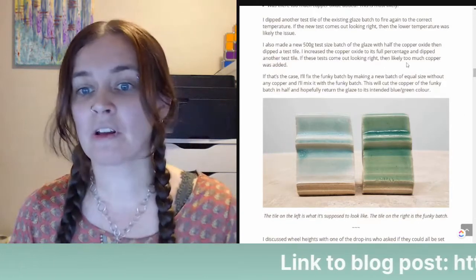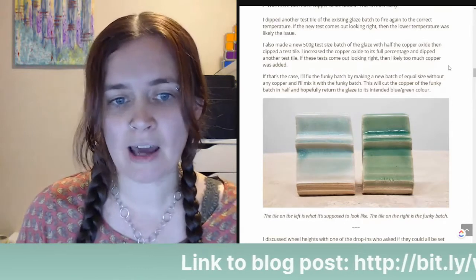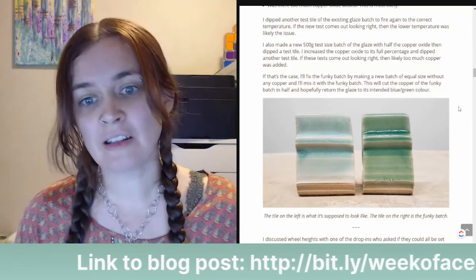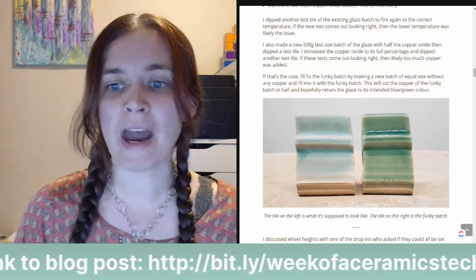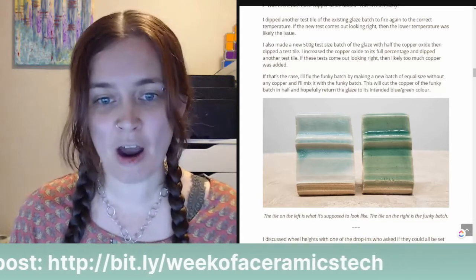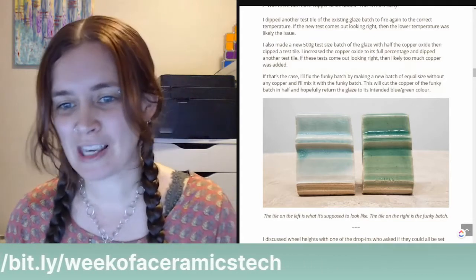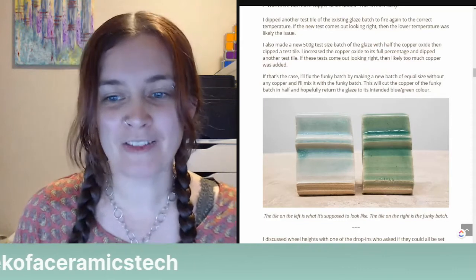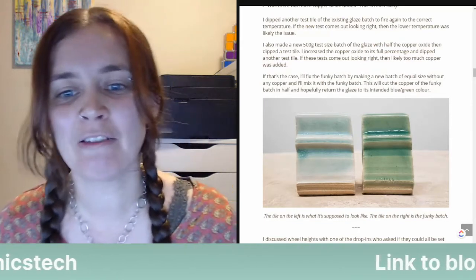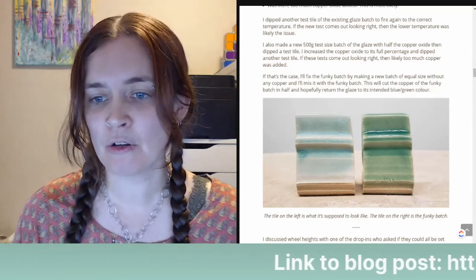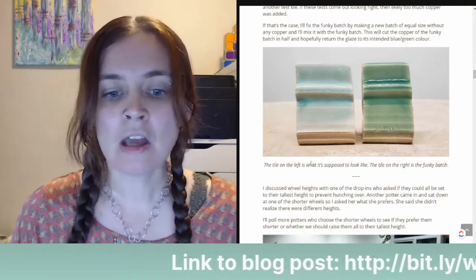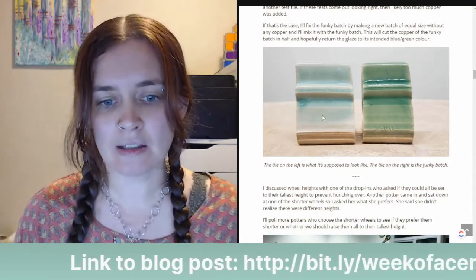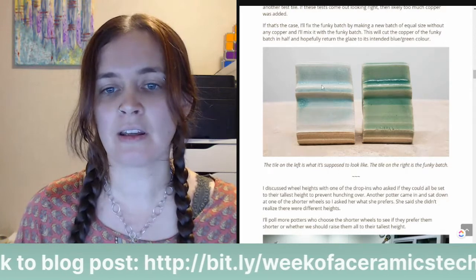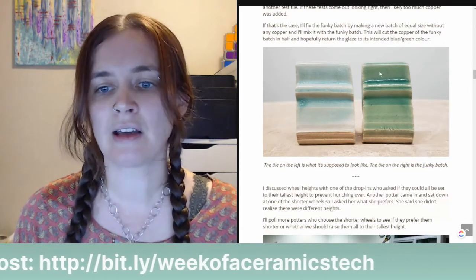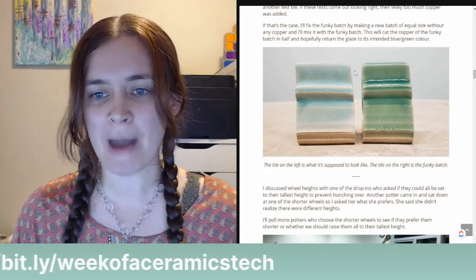If these tests come out looking right, then likely too much copper was added. If that's the case, I'll fix the funky batch by making a new batch of equal size without any copper, and then I'll mix it with the funky batch. This will cut the copper of the funky batch in half and hopefully return the glaze to its intended blue-green color. So here we have the tile on the left. This is what the glaze is supposed to look like. And then the tile on the right, this was the funky batch.